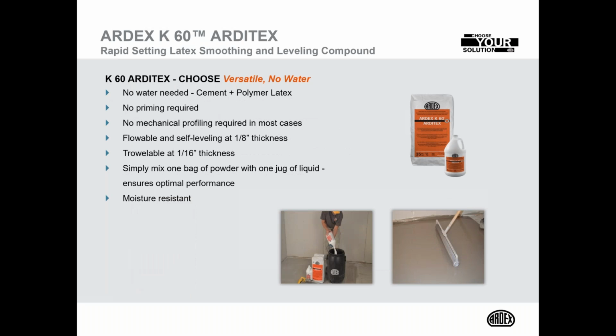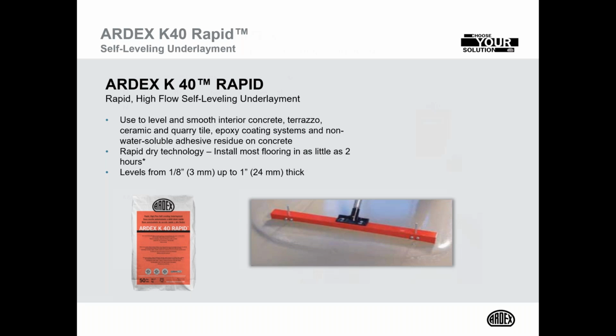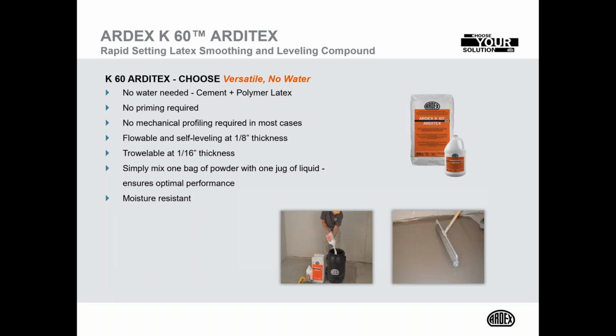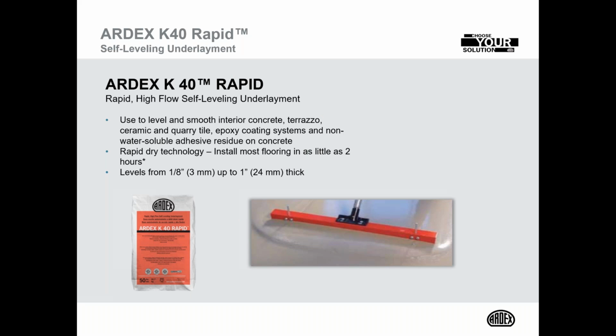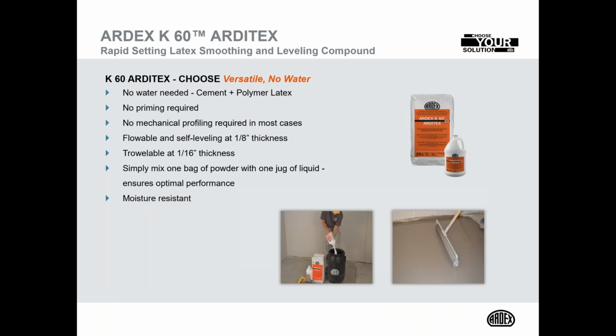Okay, it can be placed at an 1/8 inch thick, so it's suitable for that blotter layer that I was just talking about there. If you just need an 1/8 inch cementitious layer, it certainly can be used underneath the mitigation systems. One of the key things for us is we will use it as a part of our moisture mitigation family of products, especially the MC Rapid. It's an epoxy. 100% solids epoxy. The K60 will adhere to that MC Rapid without a primer. So it really speeds up the installation of treating a floor for moisture and then leveling over top of it.